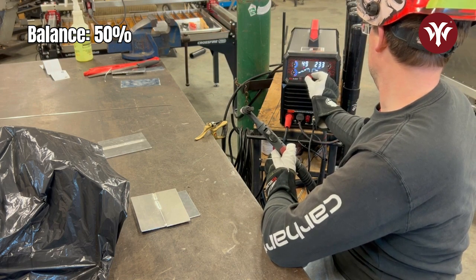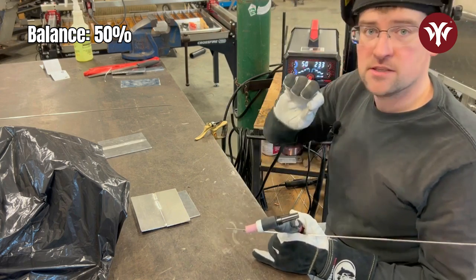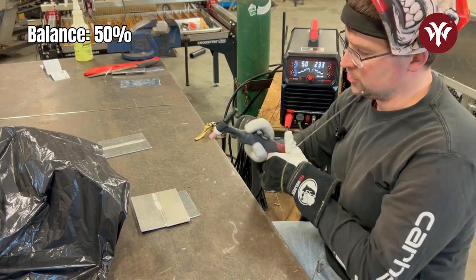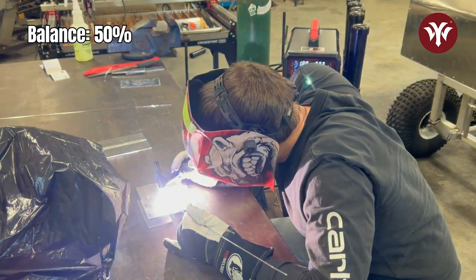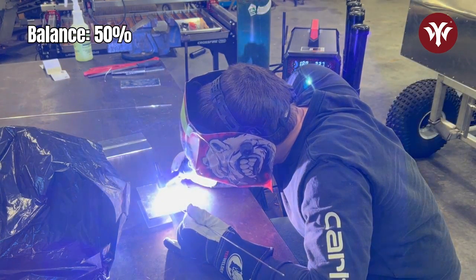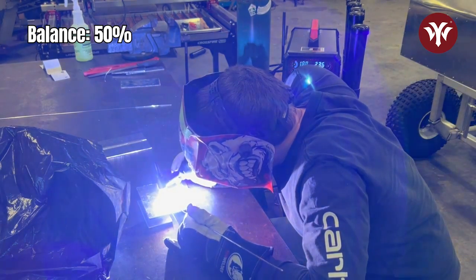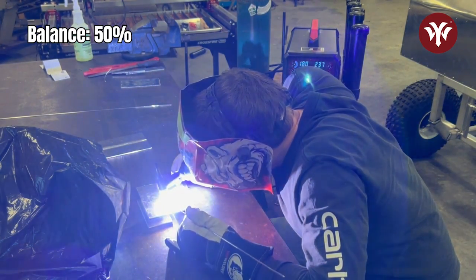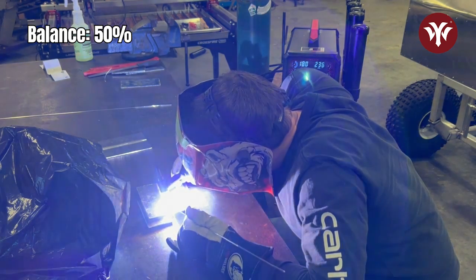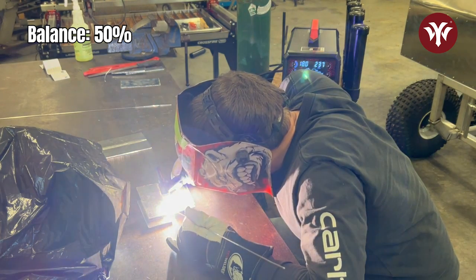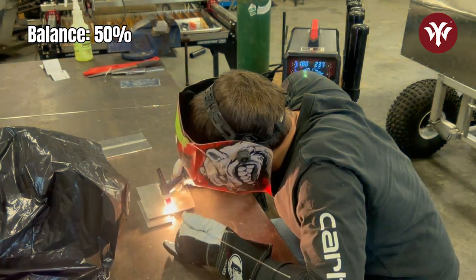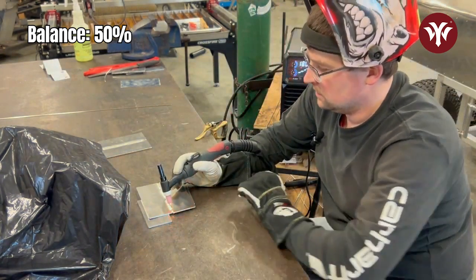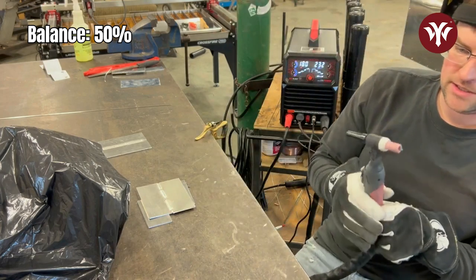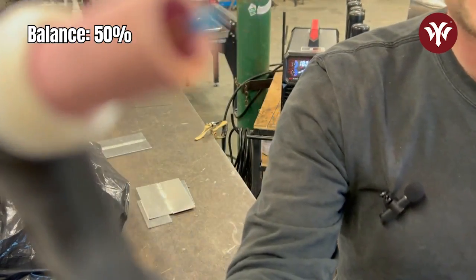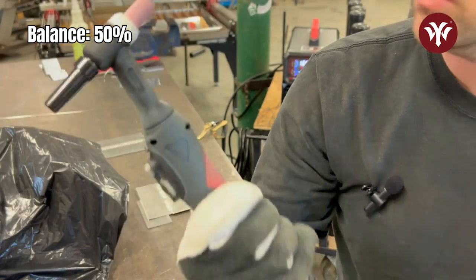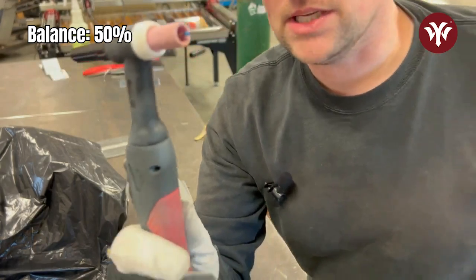Okay, let's turn it up even higher. Let's go to 50%, which 50% for a material like this is really, really high, but I want to show you. Oh, I can hear the difference. Oh yeah, I'm needing much more current. The tungsten is balling up more than it ever has because again, I'm putting way more heat into the tungsten. So it's probably a hard thing to show here, but that tungsten got a lot hotter. It actually balled up really nicely, but I probably would need more post-gas flow.